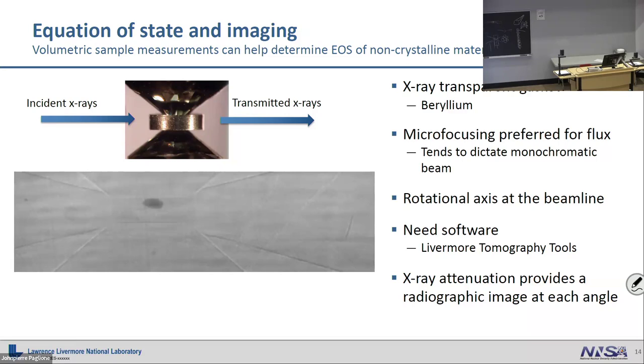What you can do here is, I said that and then I'm going to point out the beryllium. There's the gasket, there's the diamonds, you can see they're scattering comparably, and then you have the hole in the middle that's your sample chamber, and in the center is a piece of tin in this case. You can take this image and rotate your diamond around as many angles as you want, and now you're basically doing a 2D tomographic image of it, and you can reconstruct that. So you can reconstruct the volume from these dark pixels.